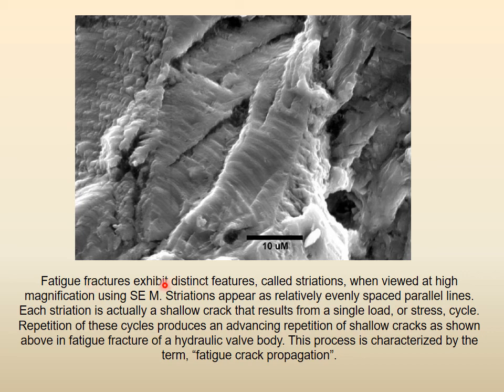Fatigue fractures exhibit distinct features called striations. When viewed at high magnification using a scanning electron microscope, striations appear as relatively evenly spaced parallel lines, right? Now this is much more enlargement. Each striation is actually a shallow crack that results from a single load or stress cycle. Repetition of these cycles produces an advancing repetition of shallow cracks, as shown above in the fatigue fracture of a hydraulic valve body. This process is characterized by the term fatigue crack propagation, right? That each crack is there and then they are propagating. So this is beautiful, right?